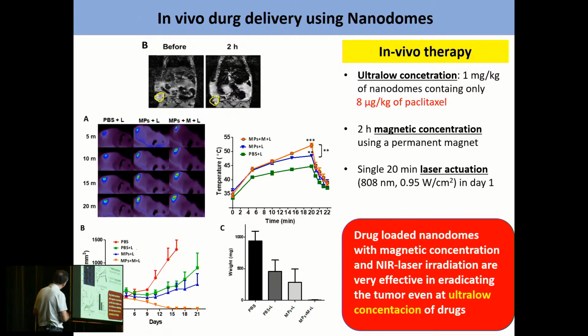on the tumor, and you see here that the laser itself on the tumor increases a little bit the temperature. That's the green curve here. When we use the nanoparticles and the laser, the temperature is increased further, and when we do the magnetic concentration, which is this one, we can increase even further the temperature. So to do the experiments, what we did was a single 20 minutes laser actuation at 808 nanometers.